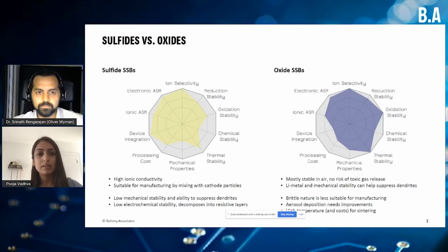The other issue is dendrite formation, which is the buildup of lithium metal. And we think that maybe harder materials with a higher Young's modulus would be better to mechanically prevent these dendrites. So these are some limiting areas of sulfides. And when you put them in a dry room, they react with moisture in the atmosphere and produce a toxic gas, H2S. So you have to be very careful about how you process them.